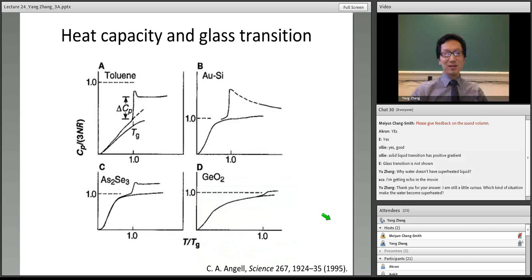Now we can start to talk about the glass transition. Since we mentioned the stability, a liquid itself is a stable liquid, and under certain conditions we can drive the system out of equilibrium and go to the metastable state. If we keep doing that to the extreme, then we end up with a glass state. In the case of water, if we supercool, like the way I did with the fridge, I can form supercooled water. But if I do it really fast, then before water can crystallize, the kinetics become extremely slow. Water can form a glass. So many materials can form glass.